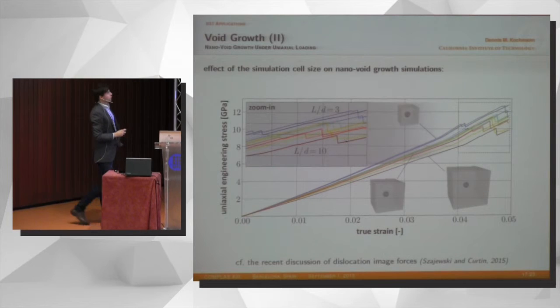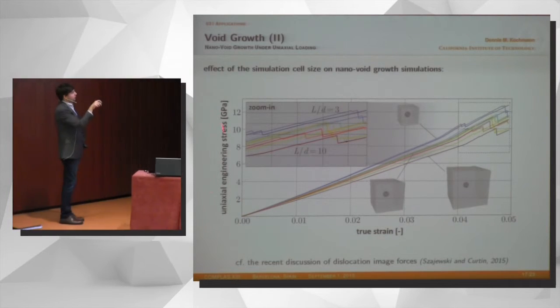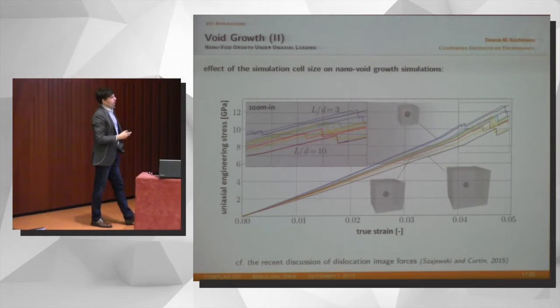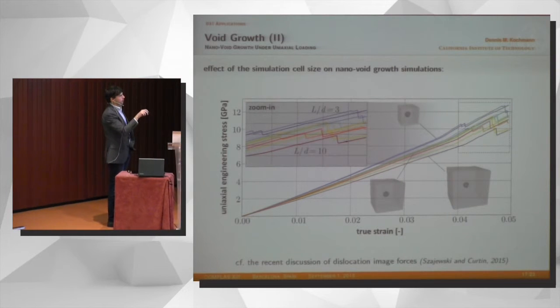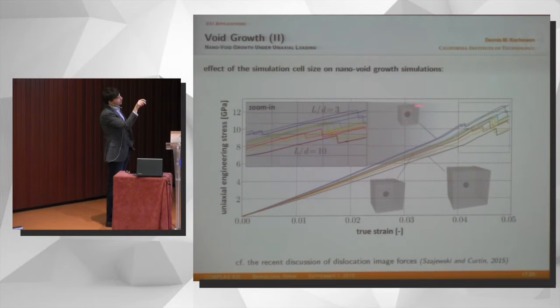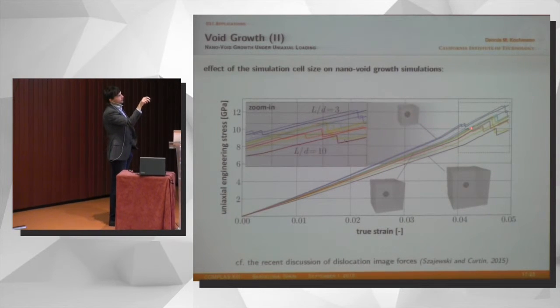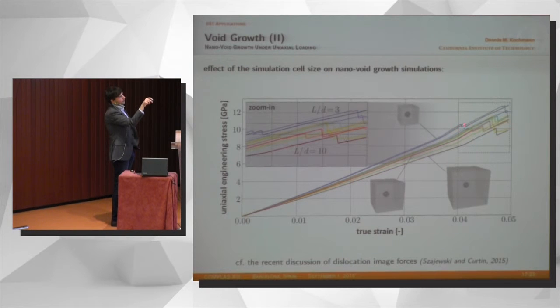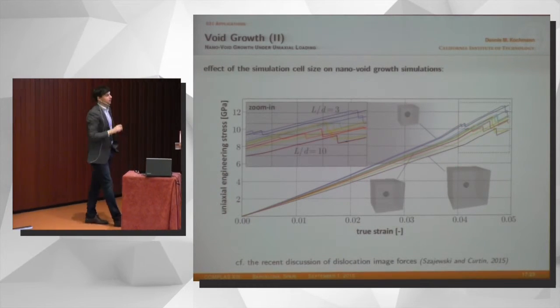And so this is what it looks like in the stress-strain response. Of course, this goes to very high strains, but this is loading in a single crystal environment, so one may expect that. So if you look at stress versus strain with the different sizes, and we tried very many different ones, we can see very different response versus locations nucleating here versus there. So there is a significant delay in the different unit cells.